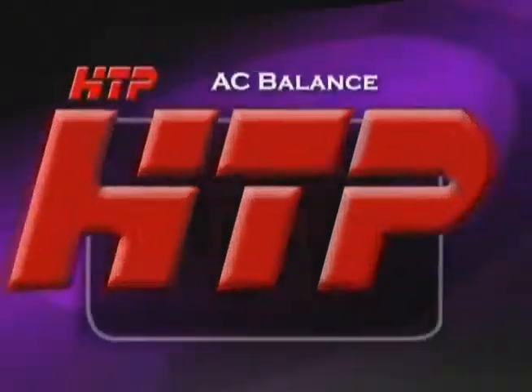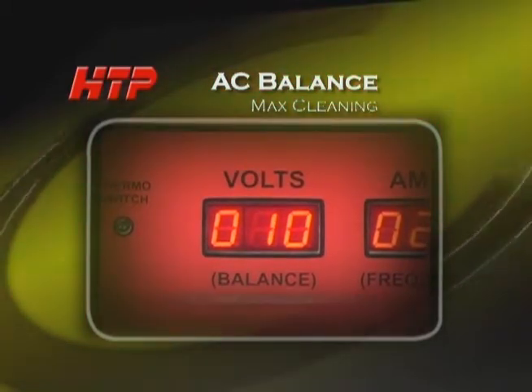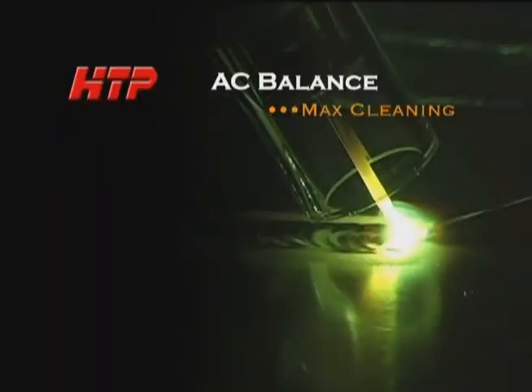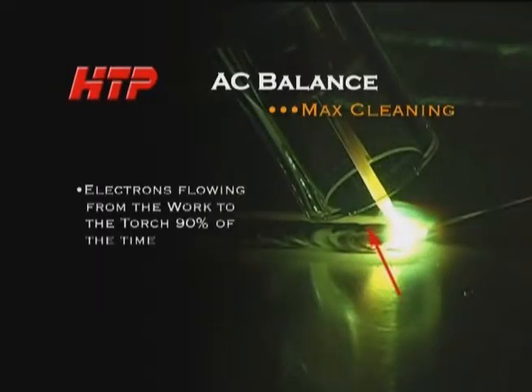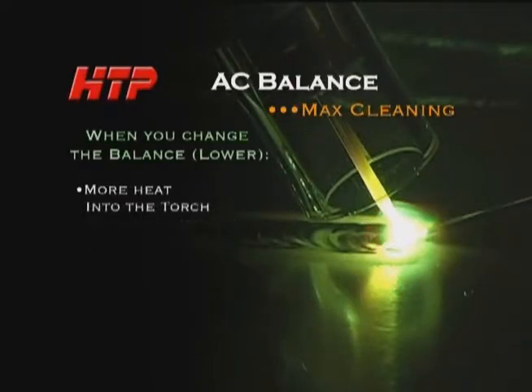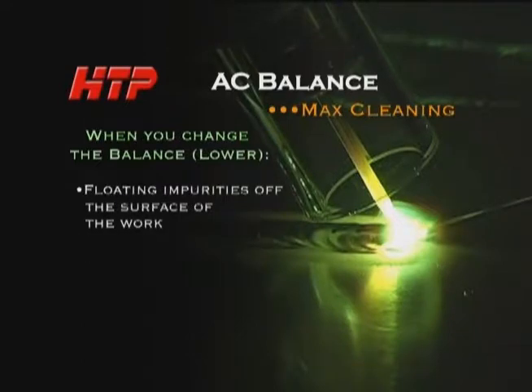Now let's set the balance to maximum cleaning, which in the case of the Invertig 201 is 10%. 90% of the time, the electrons are flowing from the work into the torch and putting the heat into the torch. You have to keep in mind that when you change the balance, you are putting heat into the torch and also putting heat into the tungsten. At the same time, this is floating the impurities off the surface of the work and giving you more cleaning action. Let's see the effect the AC balance has on tungsten heat.